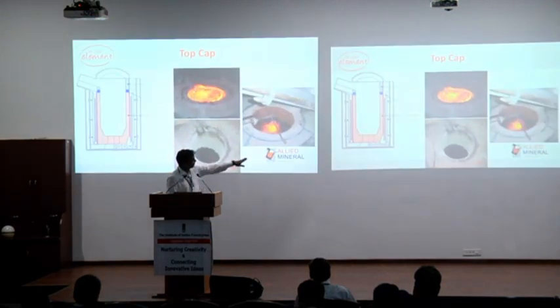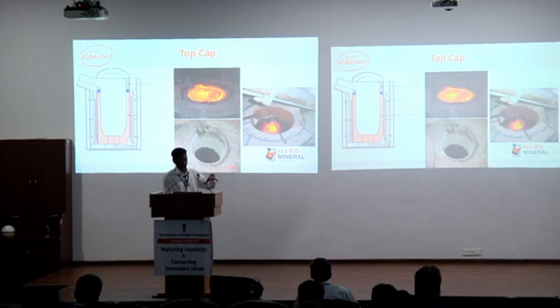So these are some pictures where we have done a dry top cap. There's no heat, nothing. It is done to the platform or to the top cap of the furnace. And normally this is the way we recommend our customers to do the top caps. So the main working lining is there and the transition layer is there. We have one bag of DV231XB, which is what we normally recommend for the top caps, along with silica. We mix it, we make a transition layer, and then we do the DV231XB on the top.